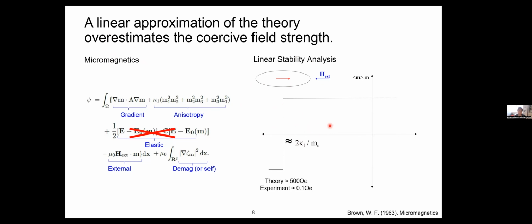So what we do in our work is to rethink how we predict magnetic hysteresis. The linear stability analysis is failing in predicting the width of the hysteresis loop, but at the same time, micromagnetics is a well-established theory. It's showing several of these phenomena, but somehow the linear approximation is not giving you the right picture of your coercive forces as well as the width of your hysteresis. And so we rethink hysteresis in terms of what we call nucleation barriers, and in terms of what we call microstructural instabilities.